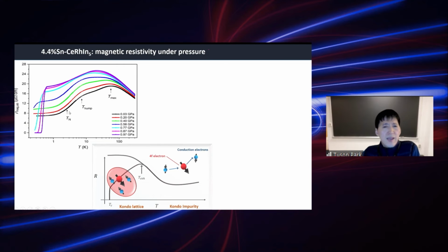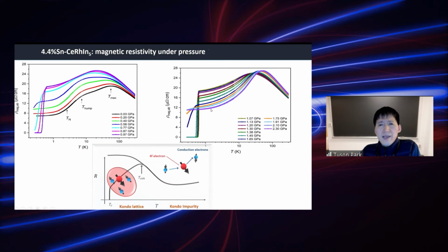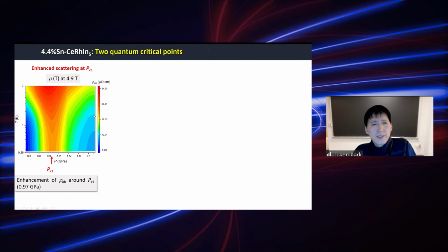With increasing pressure, the resistivity increases because of the enhanced hybridization. And at higher pressure, the resistivity still increases due to enhanced hybridization. However, at lower temperature, the resistivity starts to decrease at pressures above 1 GPa. So this is the color contour plot of electrical resistivity, and you can see a strong enhancement around 0.9 GPa, so we call it PC1.